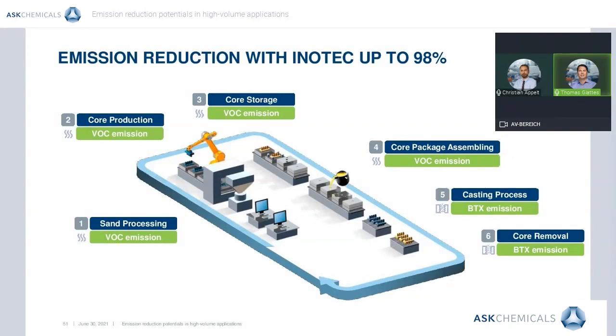In principle, yes. Inorganic binder systems are applicable in the so-called binder jetting application. The liquid binder is applied via the printhead, and the Inotec promoter is included in the sand system that is built up layer by layer. In comparison to conventional procedures using stainless steel tools with the core shooting process, the so-called printhead compatibility defines an additional requirement for the liquid binder for additive processes. The value proposition itself for Inotec as an environmentally friendly product remains untouched as the manufacturing procedures change. The same is true for the productivity increase and the metallurgical structure benefits. ASK has managed to translate these advantages from Inotec to Inotec 3D, the inorganic binder system for 3D printing.